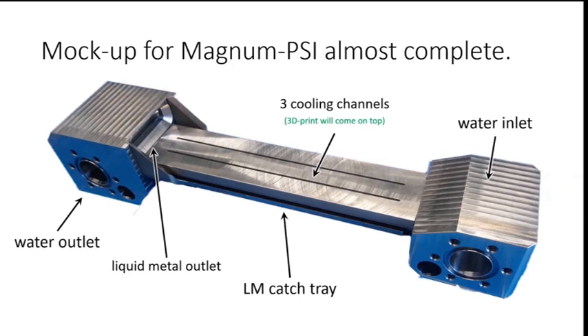So that is about 200, let's say, 400, 800 gigawatt for a millisecond, right? So you can withstand an astronomical amount of power if you evaporate enough. And indeed, it's limited by the surface thickness.